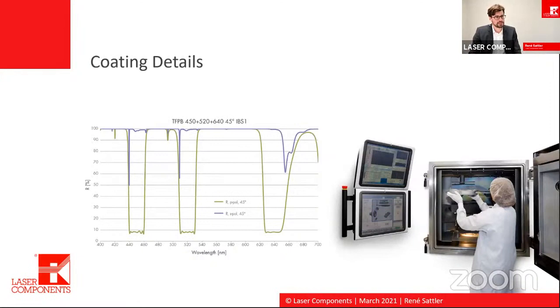On the left-hand side, you can see the spectrum. The green line is the reflection for the P polarization. You can see in the red, green, and blue wavelength ranges, we have low reflection. So the red, green, and blue is transmitted for the P pole, and the S pole reflection always remains at high values. We made this coating with our IBS chamber, which you can see on the right-hand side.